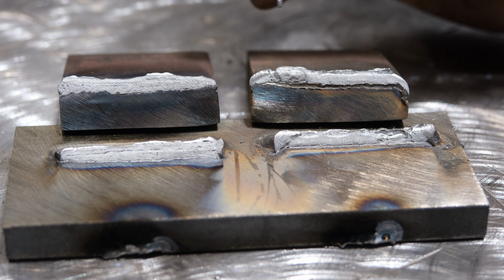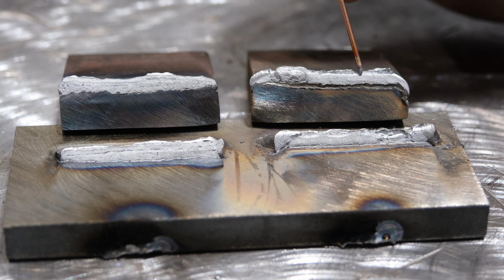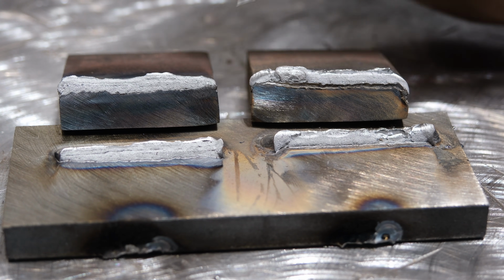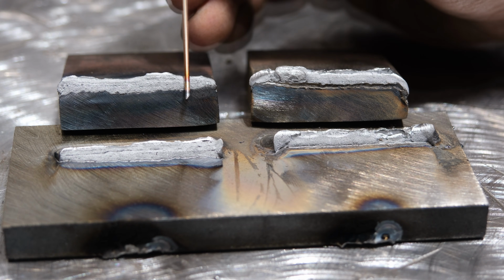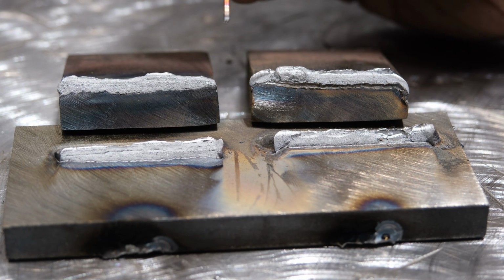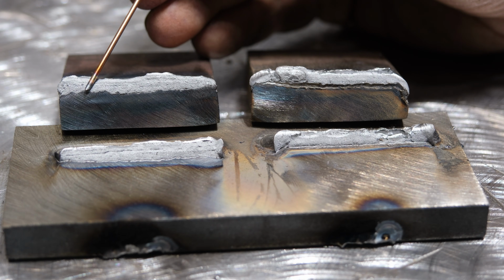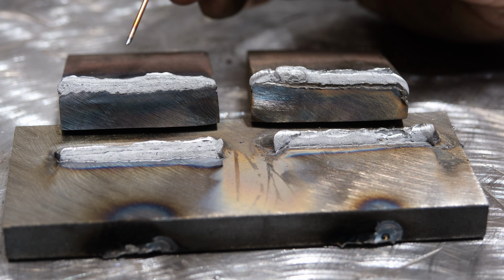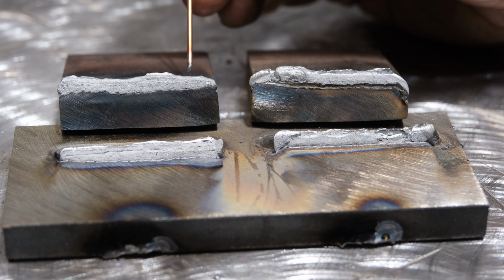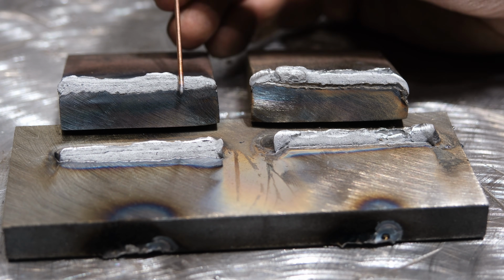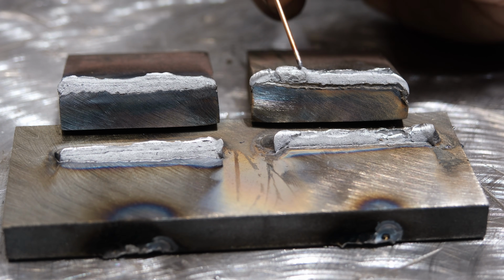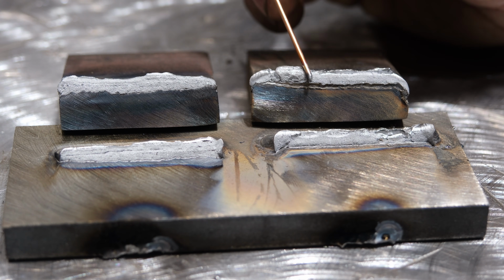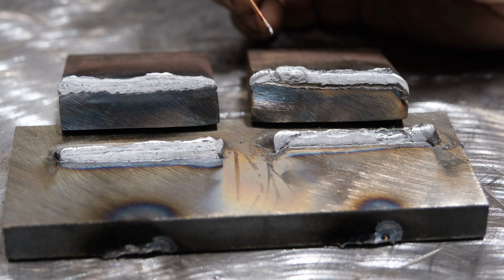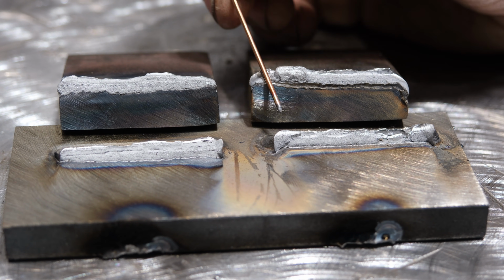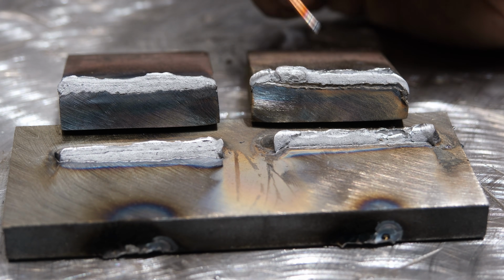Now, the other interesting thing to note here is that when you look at how clean this section is, it doesn't look that much different than this. But again, start to finish on this weld, it is far more consistent than this, and it more or less tore at a 45-degree angle, which is ideal, straight through the weld. You're never really going to see something like this on a bend test where we break it on stick or MIG unless all of these defects or discontinuities happen off of what you're welding, which again, the practicality of that is pretty limited on a lot of things you might be TIG welding, especially small parts.